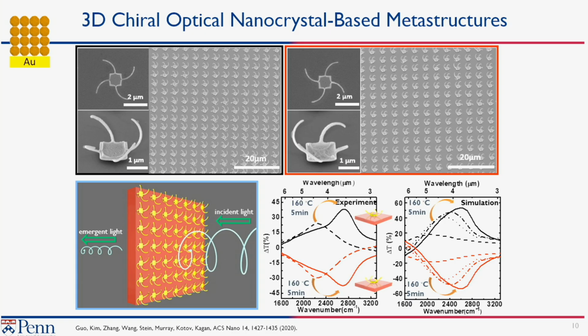It's very similar to what you've seen for MCD or other characteristics of chiral materials. And so what you'll see here is that we made the two different enantiomers, left and right enantiomers. And you can see about 0, they're mirror symmetric, right? So they should have the flipped polarity of the response depending upon the light. And so if we don't anneal these structures, and you just use the ligand exchange, we see the dashed lines here for the two enantiomers.